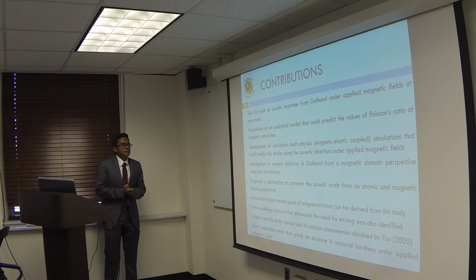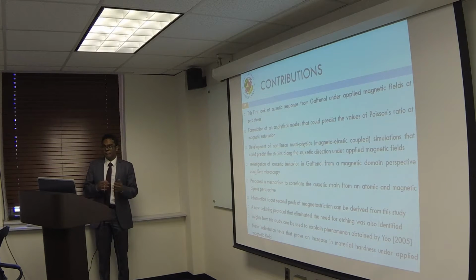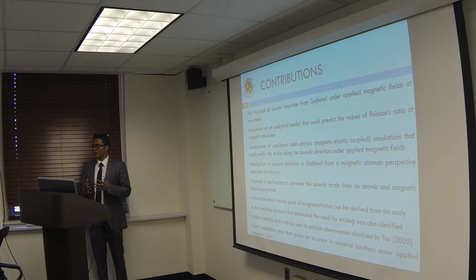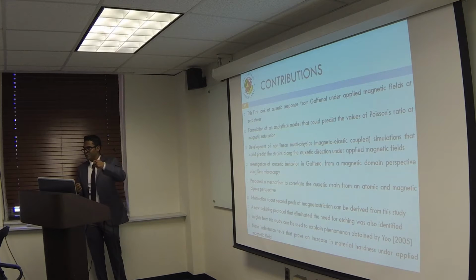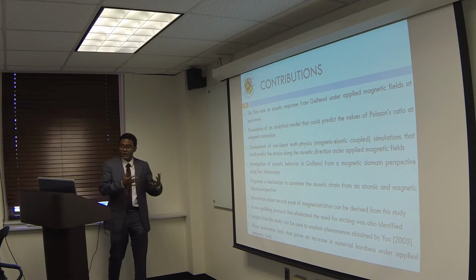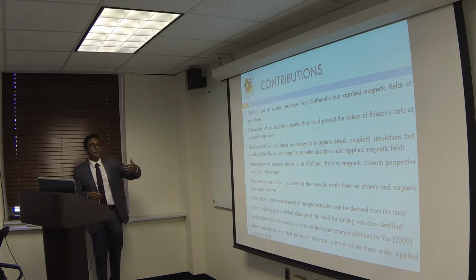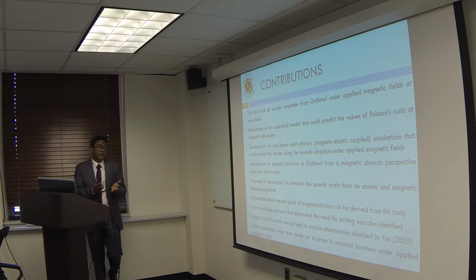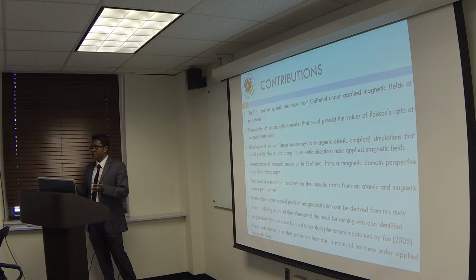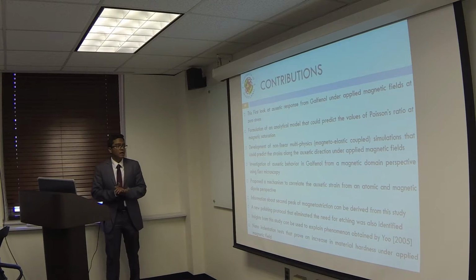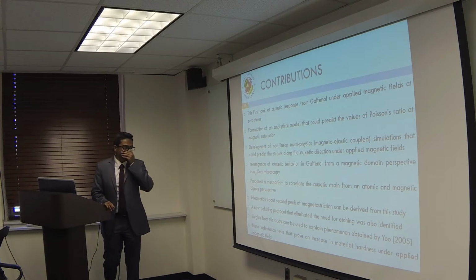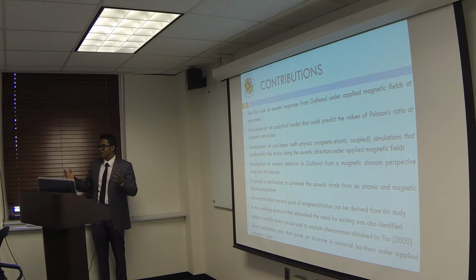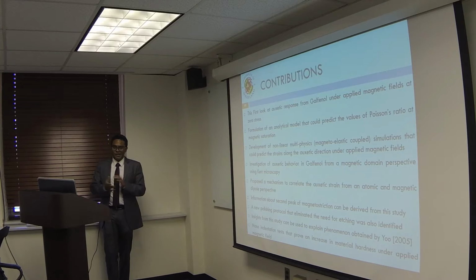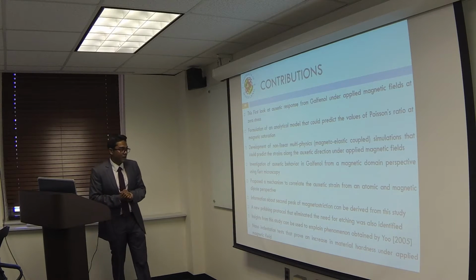Here are the contributions of the research. This is the first research ever to look at auxeticity in materials with applied magnetic fields. Traditionally, auxeticity has been associated with just stretching, and now we're able to show that there is an auxetic effect by applying magnetic fields. We were able to develop the analytical model and the multi-physics model. This is the first time that anybody has used Kerr microscopy to understand the evolution of magnetic domains along the 110 direction. We were also able to derive information about the second peak of magnetostriction, which is an area of study that has been unexplored in Galfenol.